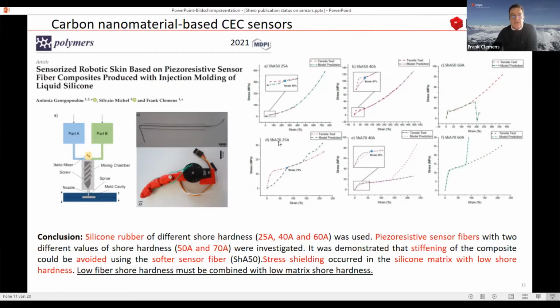And the first thing we saw is that when the fiber is too stiff, the matrix will completely stress shield the fiber, and accordingly you cannot read very useful sensor data out of it. But if you reduce the stiffness of the fiber, so this was a new fiber which we developed based on the old one, you can see that we can even go to much lower shore hardnesses of a silicone matrix, and we have a very nice match between the model prediction and the tensile test which we did on fibers. So here the composite model is working, and accordingly we also got good sensing behavior out of it. In other words, the main conclusion was that low fiber shore hardness must be combined with low matrix shore hardness. So you really have to look at those materials.